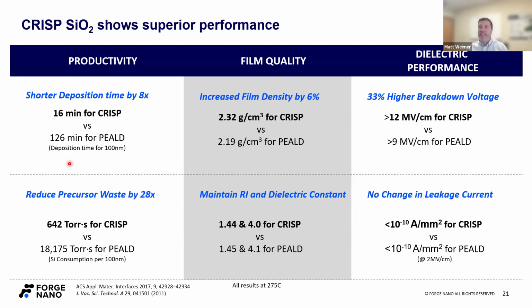And there are a couple of productivity takeaways. We have shorter deposition time. Again, this was in the literature, so I'm sure they can go faster. But I will guarantee that we are using less precursor. Maybe it's not 28 times less, but it is certainly less. From a film quality perspective, our film at 275, the density is above 2.3 gram per centimeter cubed. You can do densification of films with plasma enhanced ALD, but getting a density for silica above that is challenging unless you do a post-deposition anneal. So again, that speaks to the quality of the film. The refractive index is 1.44, and the dielectric constant, again measured on silicon, is usually around 4, which is pretty typical.